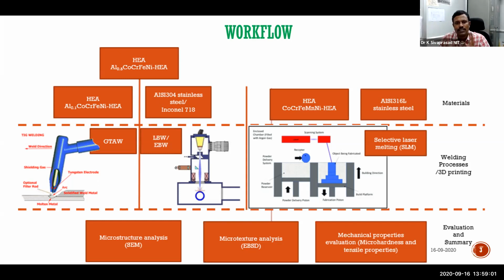Even though the system is now somewhat stabilized with respect to weldability, some laves phase and other metallurgical undesirable phase formation is still there, thereby property reduction. So we have chosen these three systems for that reason. And we have used the popular GTAW, that is TIG welding, and laser and electron beam welding combinations. The same system we could not do in SLM in Europe because they are restricting aluminum in their system. So without aluminum, we substituted manganese and started working on this one.